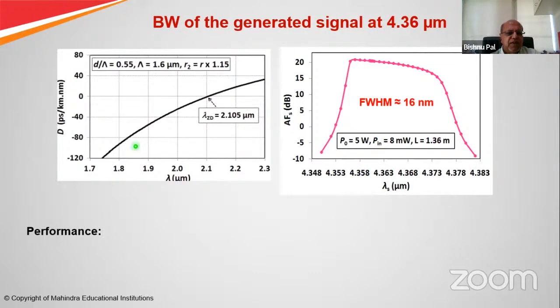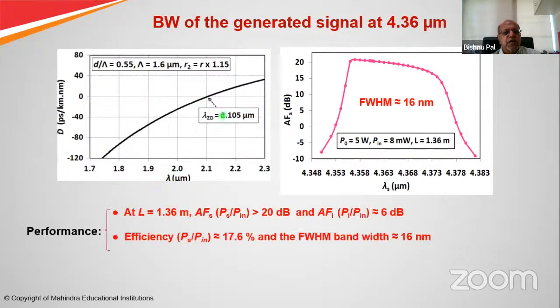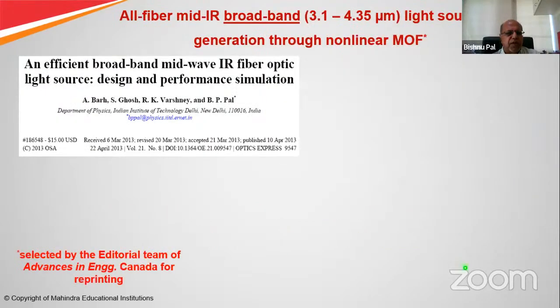And you can see the fiber has been designed to have zero dispersion close to the commercially available high power fiber laser of thulium doped fiber. In this case, it was 2.105 rather than 2.04. So this gives, at 4.36 micrometer, an amplification factor of almost 20 dB of the signal relative to the input power. And for the idler, it is only 6 dB. Efficiency 17.6% and full width half maximum of 16 nanometer.